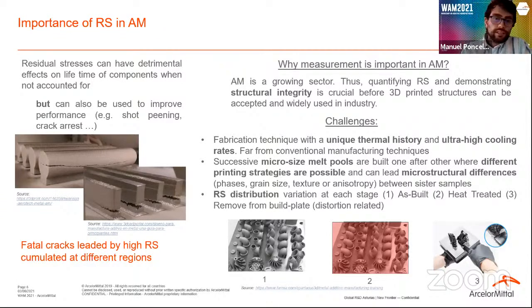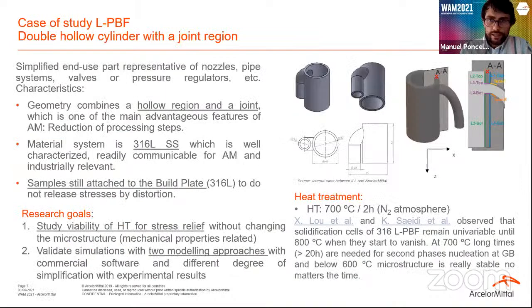So it is important to know the stresses and their distribution on the samples as built in a heat treatment if you do it for stress relief, and also when you remove the sample from the build plate to reduce possible distortion of the geometry, and also to assure the structural integrity of the component. So here I present our case of study.